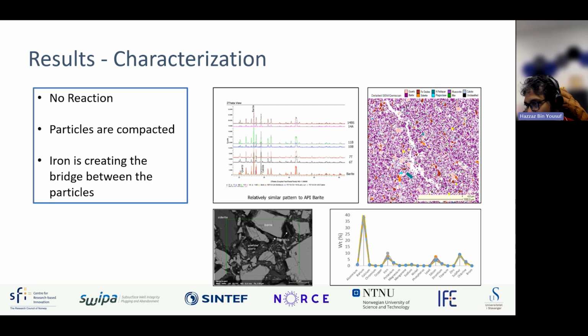It is a physical process. And we also see that there is no cementation. The particles are very, very compacted, but they are really strong. So we tried to look at the elements, and we found that there is one element that is completely new. It was not in the cuttings. It was not in the drilling fluid as well. The element is iron. We have seen a large amount of iron in this material.